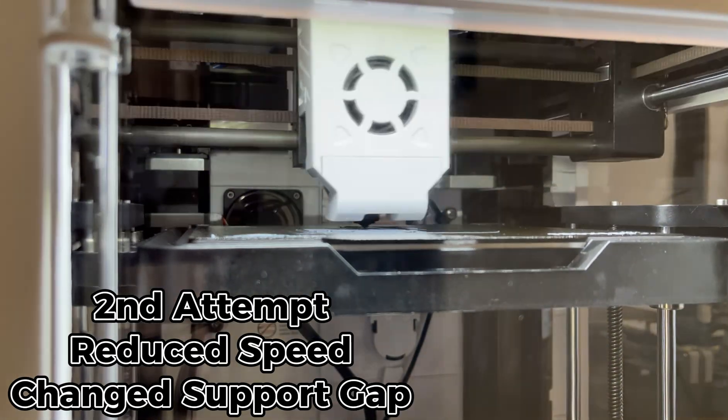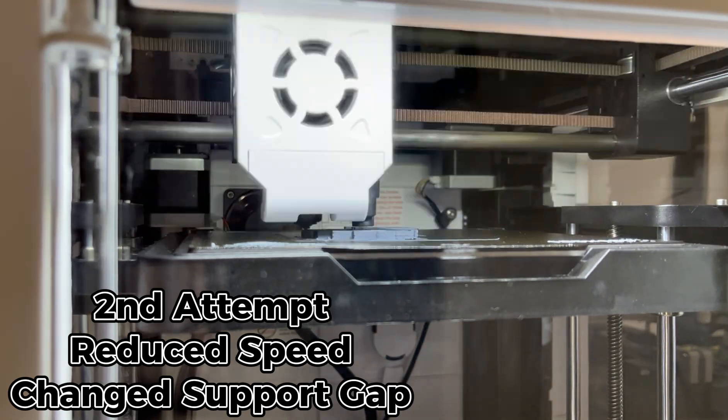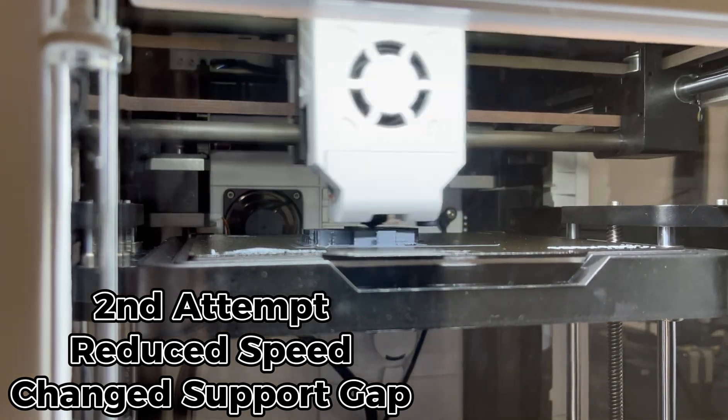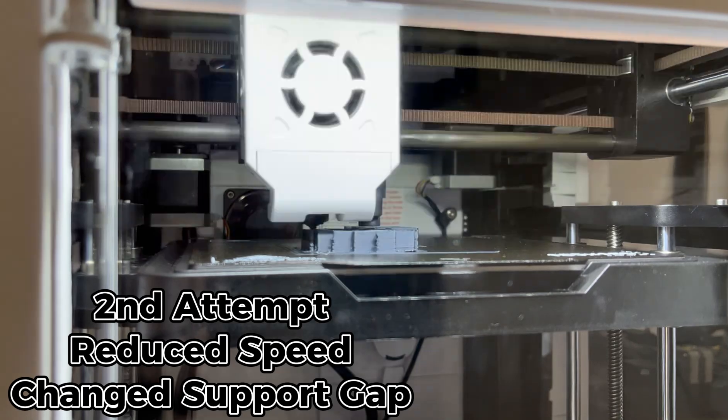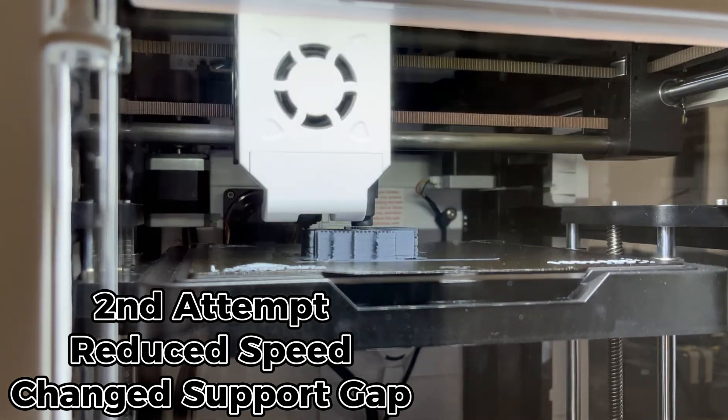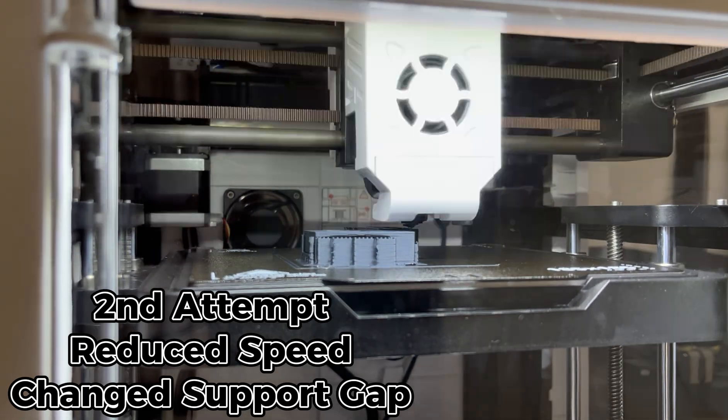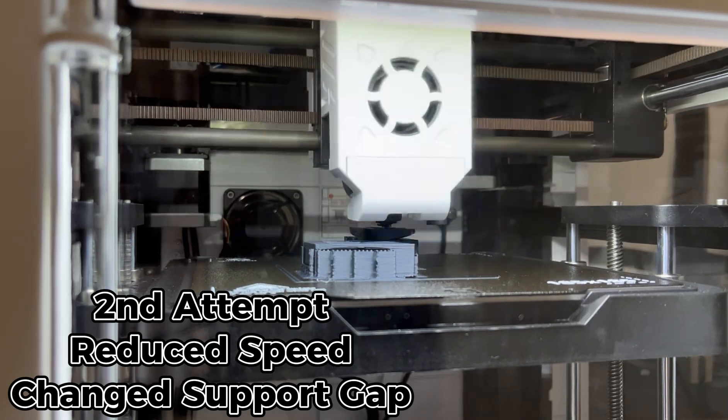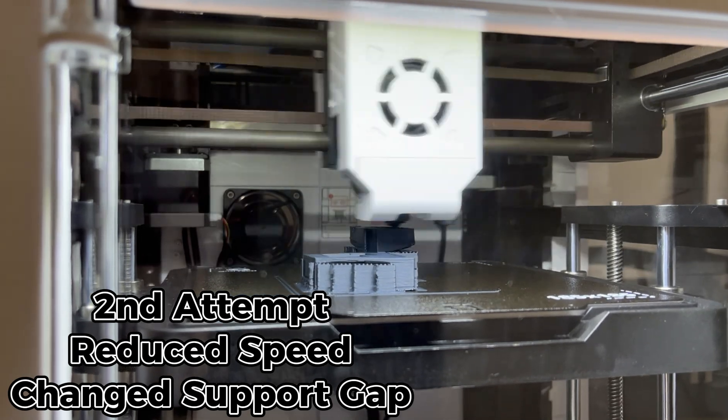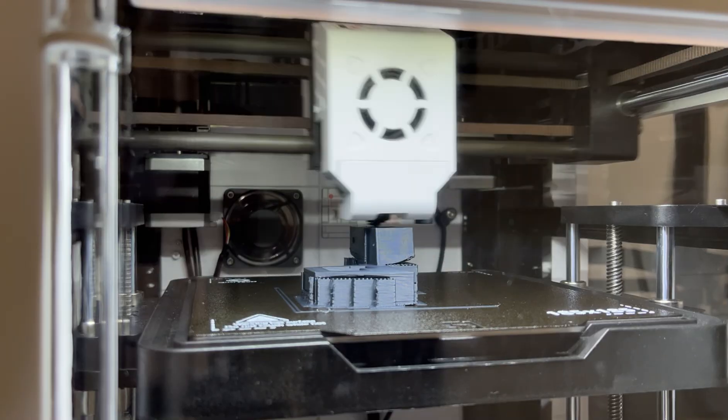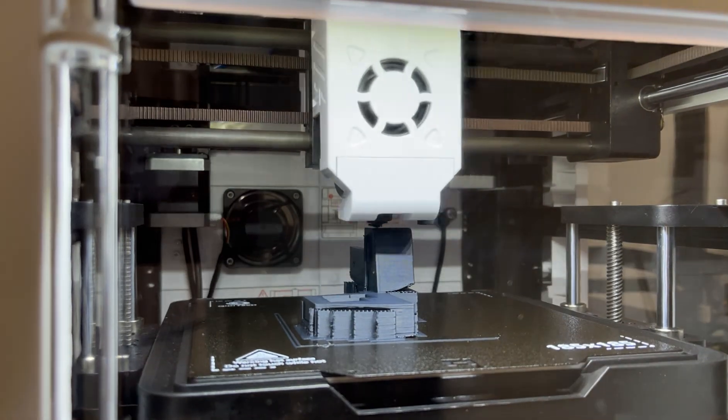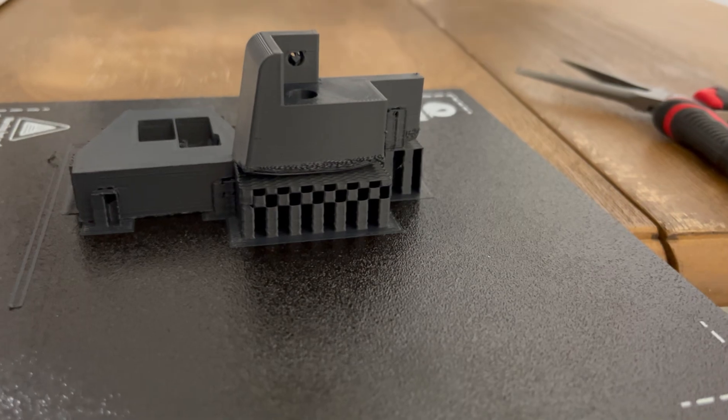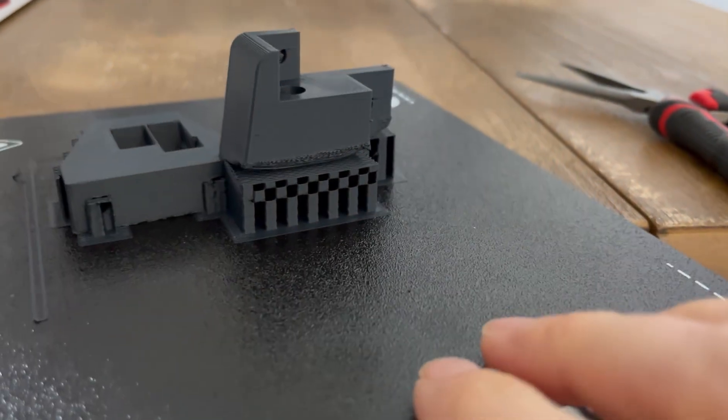Starting another print, I slowed down the printer's speed when it was printing, increased the gap between the supports, hoping to give me more surface for the layer to stick to. And with the lower speed, I'd hoped to be able to allow the ASA filament to melt fully onto the support layer. Did it work? Of course not.